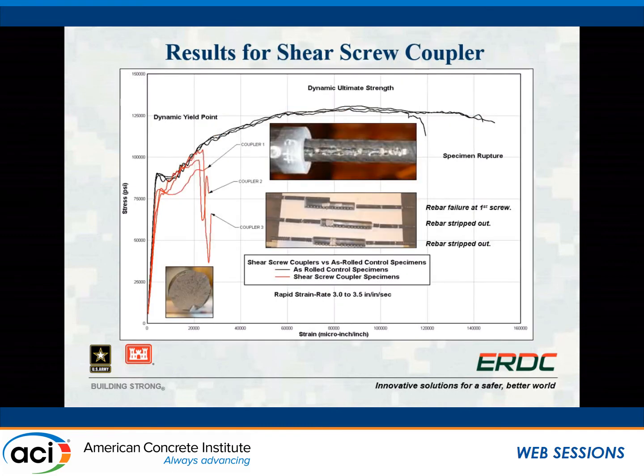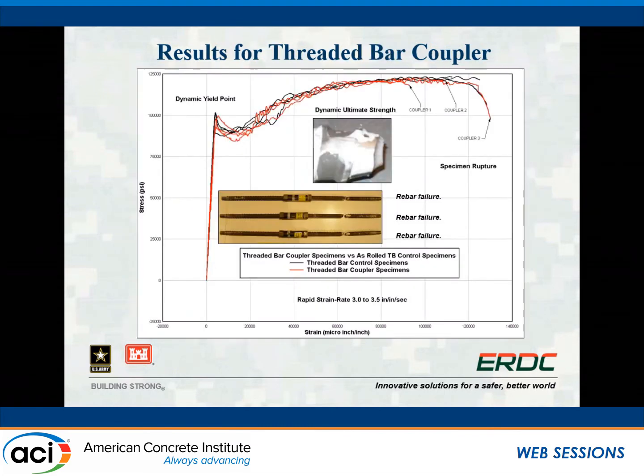The shear screw couplers all behaved in a similar fashion, especially at dynamic strain rates. We'll see some actual quantitative results from these. But for all of these tests, we saw significant reductions in tensile strength and ductility, and they were very consistent between each sample, where in general the rebar just pulled out of the coupler at lower strength levels and lower percent elongations.